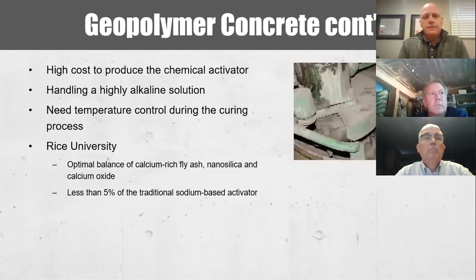Like I said, the drawback here is that there's a high cost to produce the chemical activator, and handling high alkaline solution, it's just like handling a high acidic solution, very difficult. And you oftentimes need temperature control during the curing process. So ideally, at least at first here, there's an application for precast concrete.